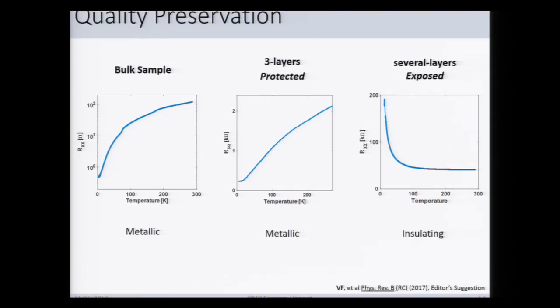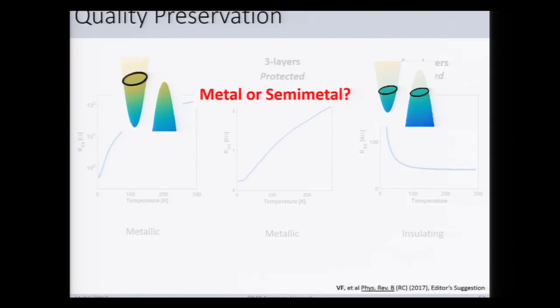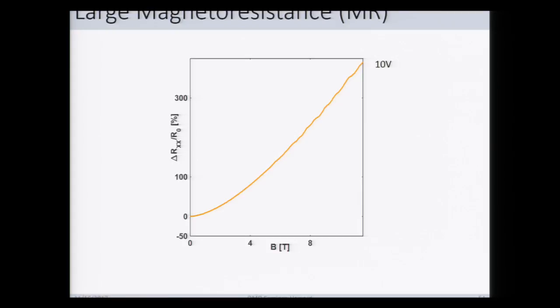And the next thing we want to know is, is it a metal or semi-metal? For example, did the fabrication procedure dope the system, or did something else happen, or does it look like the bulk samples like we would like? And one of the ways we can do this is with magnetoresistance. So just to start, we see very immediately this is the relative change in resistance as a function of magnetic field, and we see this nice nonlinear increase that doesn't quite show any signs of saturation up to our largest magnetic fields that we can apply.